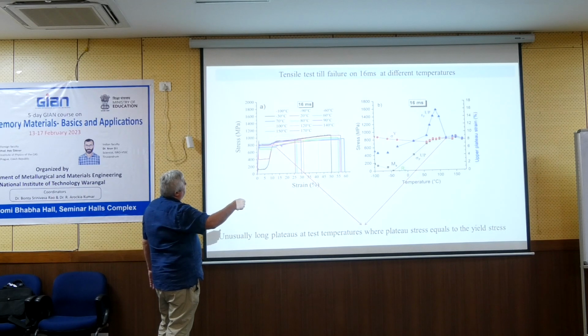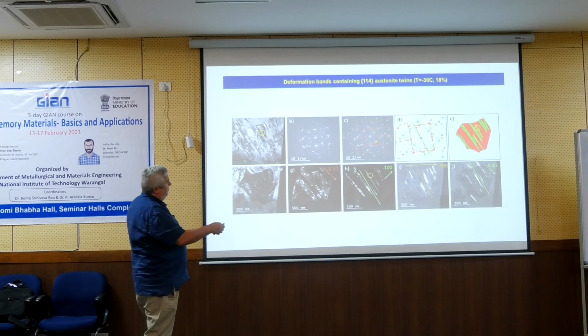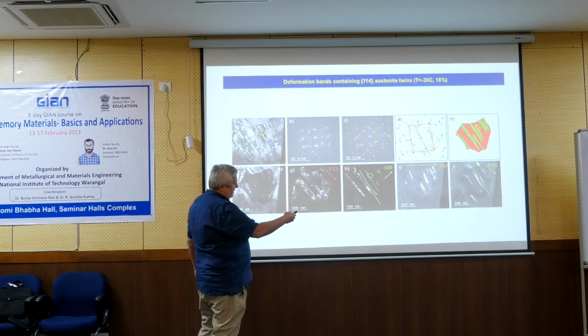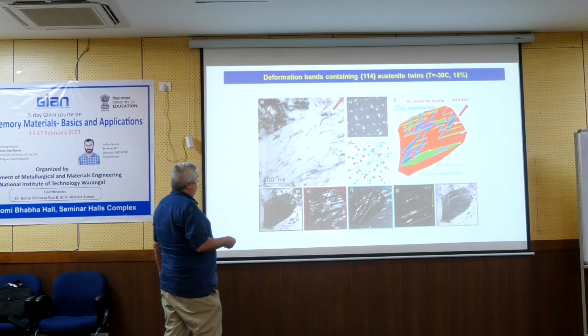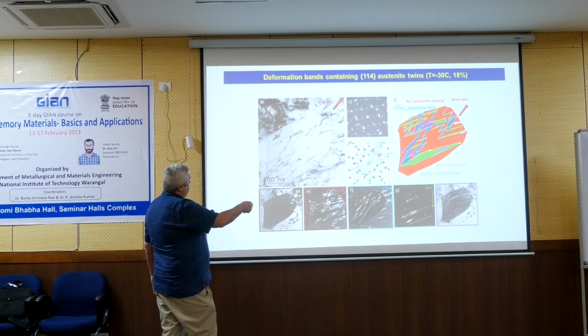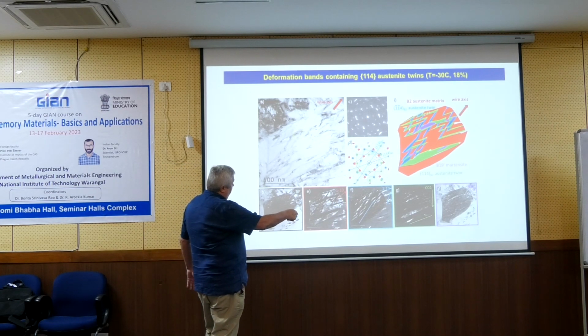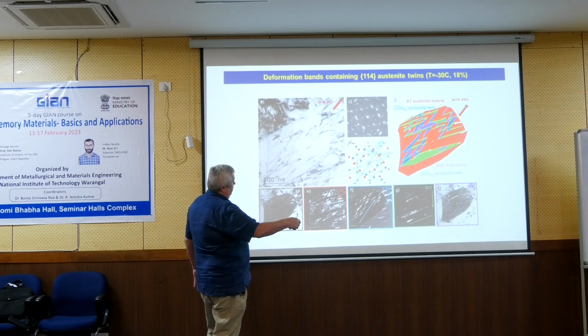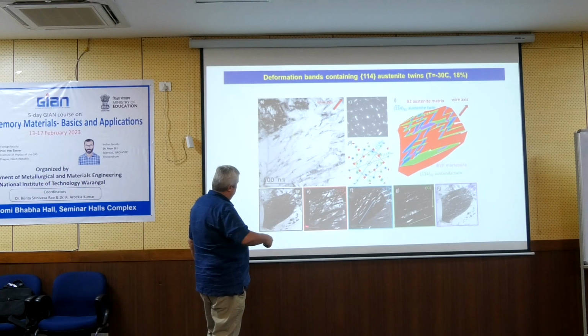We deformed up to different maximum strains. So if you deform up to 16%, then in the wire you will find the microstructure like this, or even better like this. So these are the bands where the austenite lattice is differently oriented, and this is the confirmation from the TEM analysis. The red is the matrix, and this blue and green are these bands, the twins.